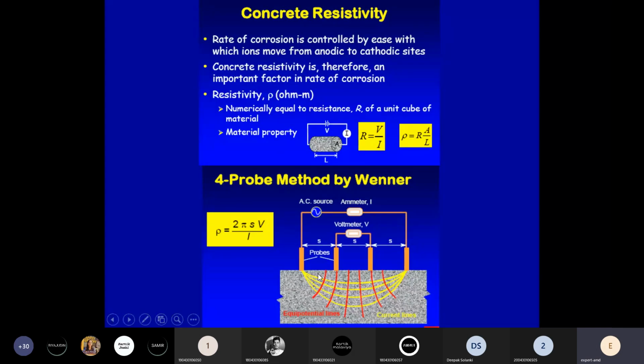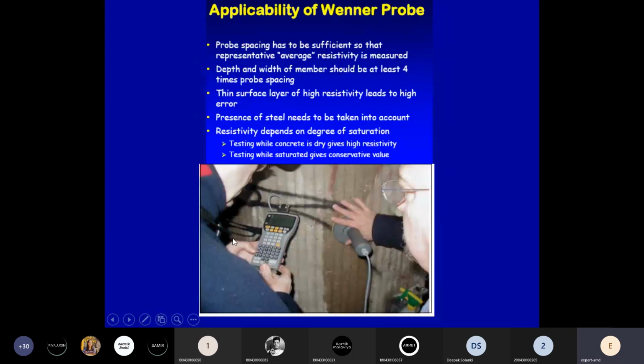So simply we use this equipment where 4 probes are placed. Then we have a voltmeter, then we have an ammeter, and we record the data. On the basis of data, there is a BS standard, BS 1881, where guidelines are given. Also, the manufacturers provide guidelines that if your resistivity is greater than 12 kilo ohm centimeter, it indicates resistivity is high and the likelihood of corrosion is lower. If your resistivity is on the lower side, it basically indicates that there is a problem with respect to durability. There will be a possibility of corrosion in future.